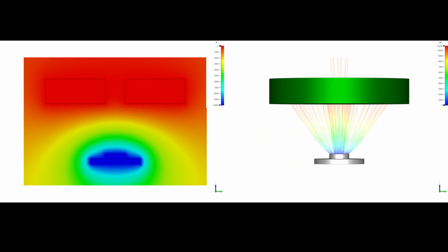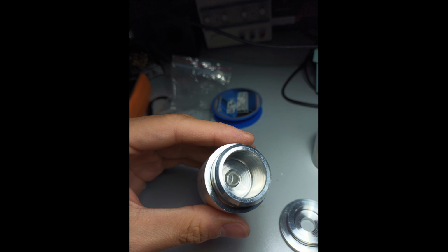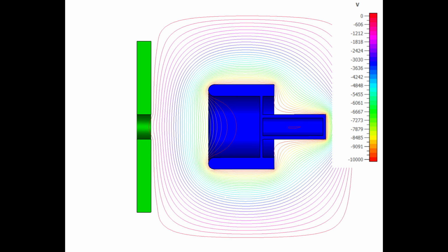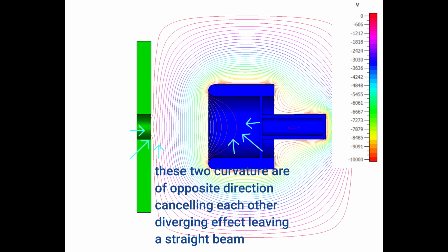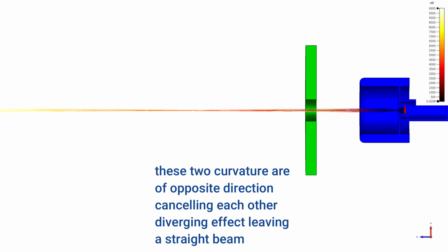But with the long fine focus design I made for this gun, instead we have the cathode body at cathode potential that protrudes from the plane of the cathode where the filament is placed, creating an initial intrinsic converging effect onto the electrons that are repelled away from the cathode potential walls inward toward the center, and this effect, added to the natural diverging effect of the anode aperture, gets cancelled out, leaving us with an almost perfectly collimated beam.